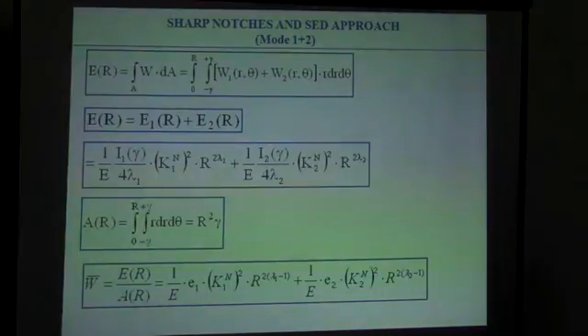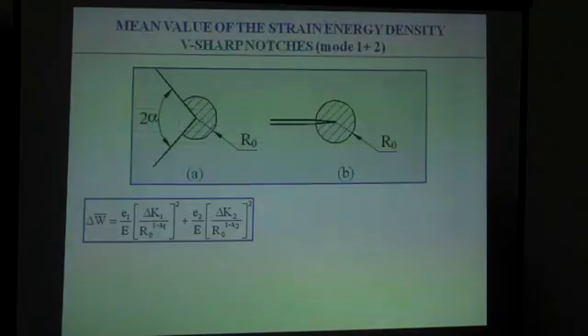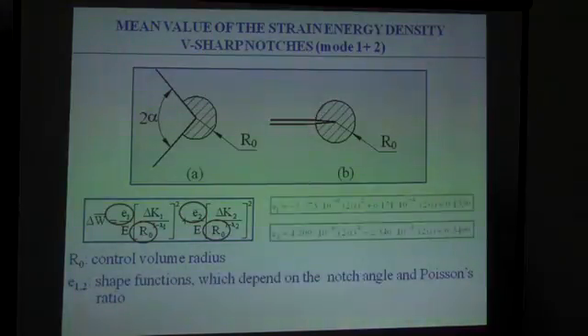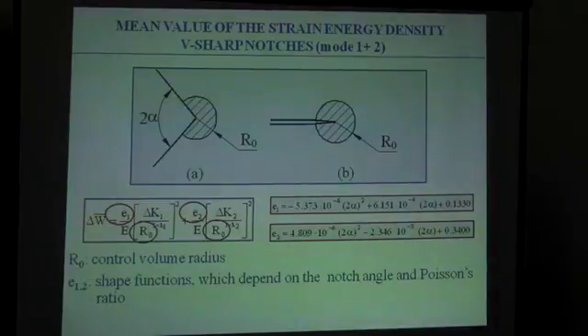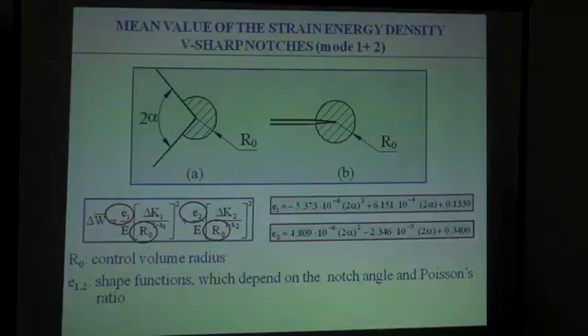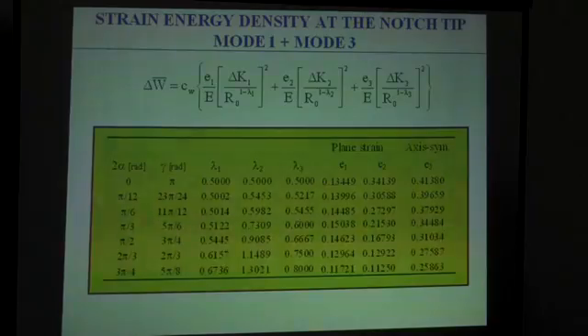density, the average strain energy density, as a function of the notch stress intensity factor of mode 1 and the notch stress intensity factor of mode 2, when we are considering in-plane shear stress. And it is easy to evaluate the range of the stress intensity factor considering the range of the notch stress intensity factor. In particular, we have some simple equations which provide the shape functions e1 and e2, which are linked to the notch opening angle as a function also of the Poisson's ratio. These equations are valid only for a Poisson's ratio equal to 0.3.